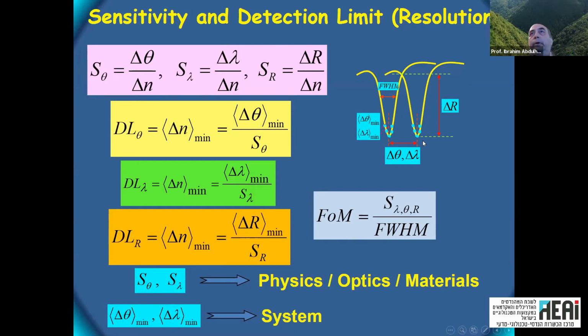If the curve is very narrow, then we get a very big change of the intensity. So the intensity sensitivity will be delta R over delta N, which can approach almost 100% variation for a very small shift, given the narrow width of the resonance. So the narrower the resonance, the more sensitive it is in terms of intensity. So this width is a measure of the quality of the sensor by the end. People define the figure of merit, almost like any other resonance, as the sensitivity divided by the full width at half maximum. So the larger the sensitivity, the better. The smaller the width, the better the figure of merit.